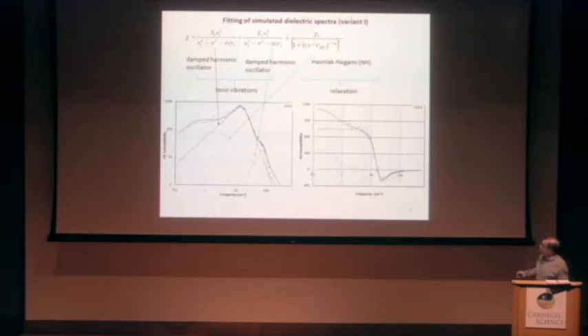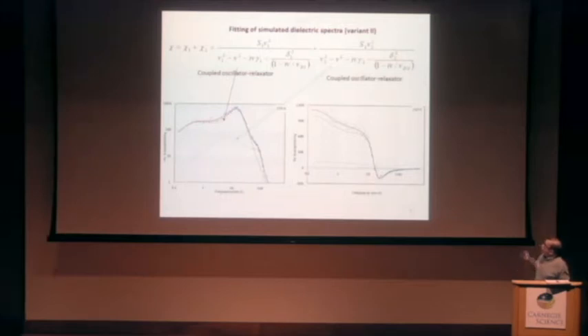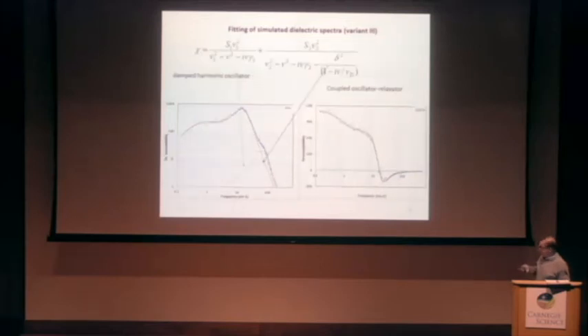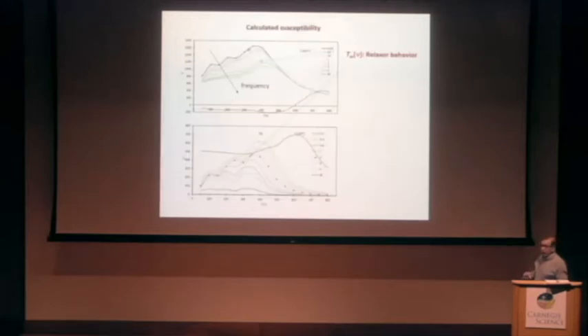You see the fitting is quite good everywhere except very high frequencies. This is the usual and known problem when the relaxation and oscillation frequencies are close. It is hard to describe them simultaneously. Thus, we use this general model, which combines two coupled oscillator relaxators. Each term contains the contribution of oscillations and relaxations, and sometimes this equation depends on our aim, which part of the relaxation spectrum we fit. And these are the results.